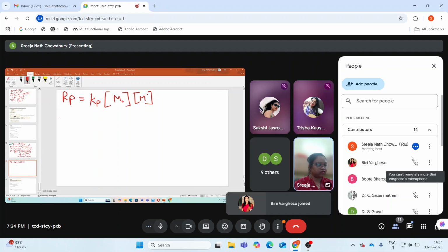So it will become ln 1 minus 0.2 divided by ln 1 minus 0.1 equals I 0.2 by I 0.1, whole to the power half.